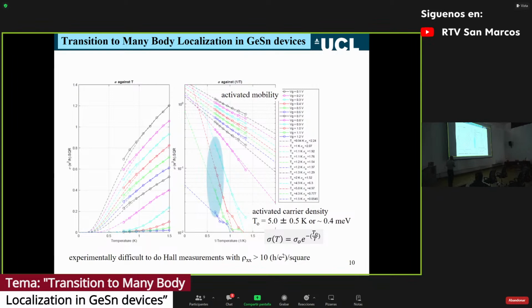So, as I said, we've got this activated mobility. This is a slightly different set of data. This is a device conductance now as a function of 1/T. It's a different measurement to what I showed before, but you can see it's nicely activated. And then this data here is where we get this sudden drop in the conductance. It's still activated, it's still thermally activated, but we think what's happening here is we're opening up a gap in the density of states. Okay, I'll come on to that.